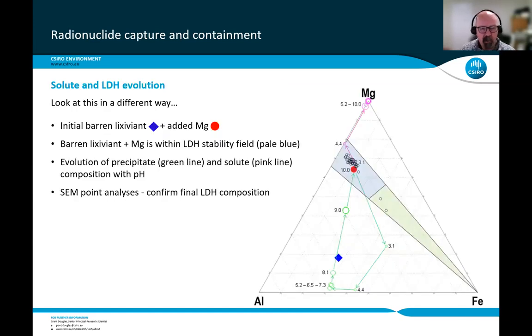So if we look at this now in a different way, and this takes a little bit of understanding, we've got a ternary diagram here on the right. We've got magnesium up the top, iron on the lower right, and Al on the lower left. Now, if you look on that ternary diagram, we have the initial barren lixiviant there in the blue diamond down near the bottom. And once we've added the magnesium to it, we have the red dot. And that red dot sits within a pale blue area, which is effectively the stability field for layered double hydroxides within this magnesium, iron, alumina ternary space.